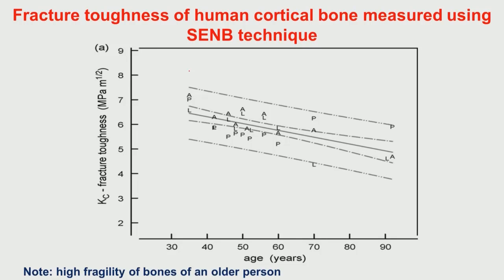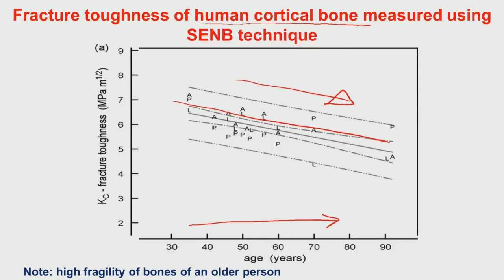So, this particular slide essentially plots the fracture toughness values of the human cortical bone, measured using the single edge notch beam technique. What you notice here is that along the x axis, the age of different patients from which these cadaver bones were taken is plotted, and then they measured the fracture toughness. So, there has been a general trend that the higher the age of a patient, there is a general decrease in the fracture toughness with increase in age.